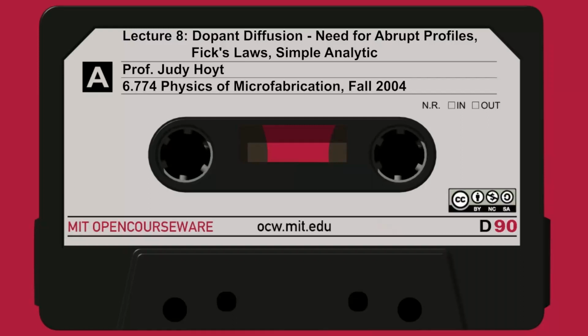So this As4V is a complex that people have hypothesized, which would enable you to introduce 4 arsenic atoms in the vicinity of a vacancy, and yet no free electrons will be donated. So these 4 arsenic atoms would be essentially electrically inactive, and yet essentially on substitutional lattice sites at high arsenic concentration. So this might be one way of accounting for the fact that the electrical solubility is a little lower than the solid solubility.